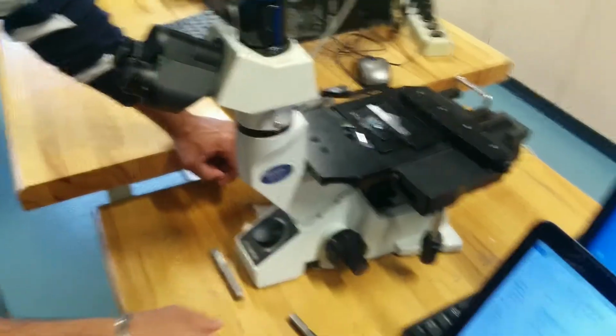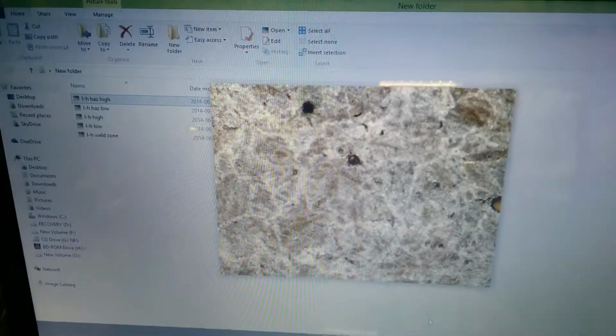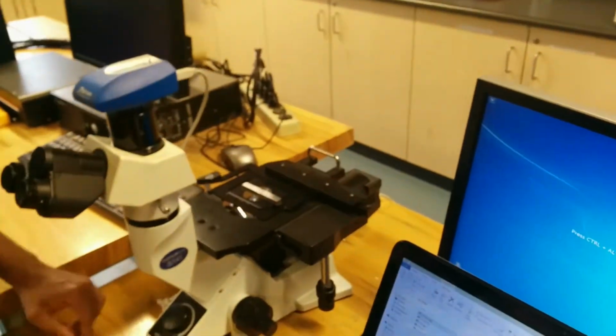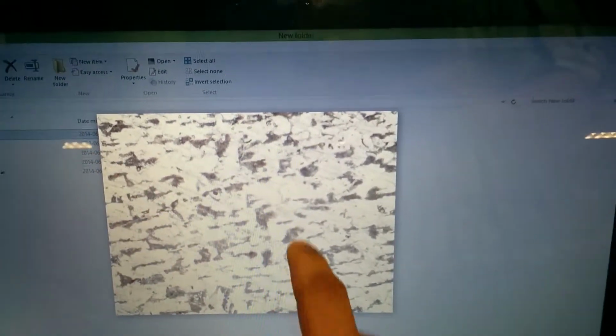Here we can see the picture of the material under the microscope. Actually, we recorded the pictures earlier, and we have the samples. So this is the heat affected zone. It is showing a very large amount of carbon, and a small amount of rust because there might be some impurities on it. Therefore, this is the low carbon zone. It has a large grain size and equally distributed carbon grains. The white grains are called ferrite, and these black grains are carbon. So these are large grains. You can see that this grain size is too large compared to the high carbon zone.